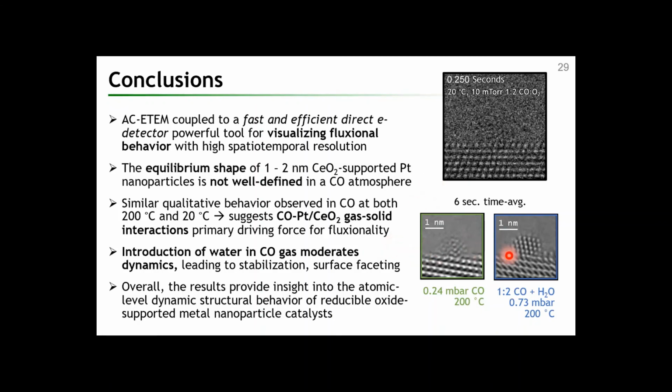Introducing water to the CO atmosphere moderates the dynamics, leading to stabilization of the nanoparticle and faceting. Overall, these results provide insight into this atomic-level fluxional behavior that occurs on these reducible-oxide-supported metal nanoparticle catalysts.